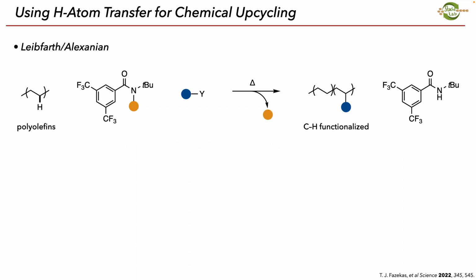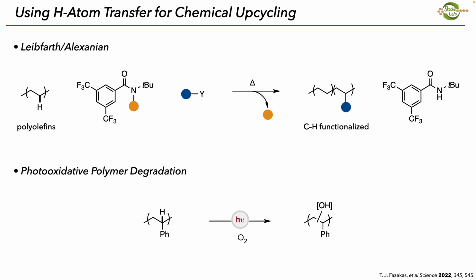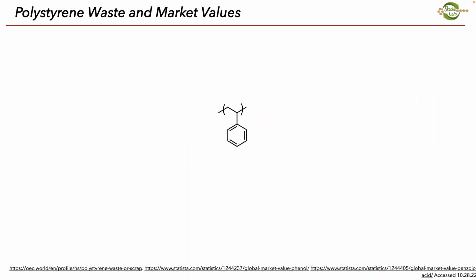And so there are other groups that have worked on this chemistry that have upcycled polyolefins like polyethylene using CH abstraction to get functionalized polymers, which have now new material properties. What people have looked at for a long time is photooxidative polymer degradation. So I mentioned at the beginning that polymers don't break down very quickly in the environment, but when they do, it's through this photooxidative mechanism. And so they absorb UV light, they react with oxygen, and then they can start to oxidatively cleave the backbone and fragment into smaller pieces. But no one's ever studied what they fragment into or tried to control how they fragment.